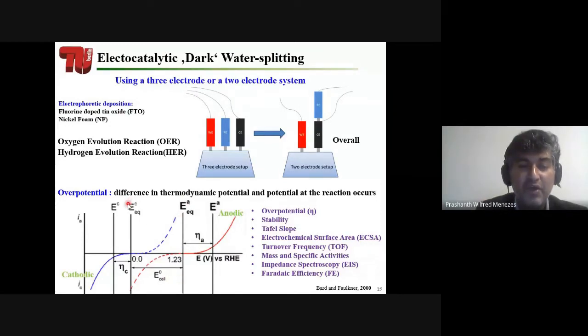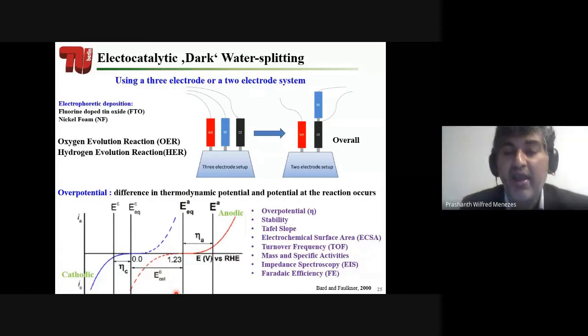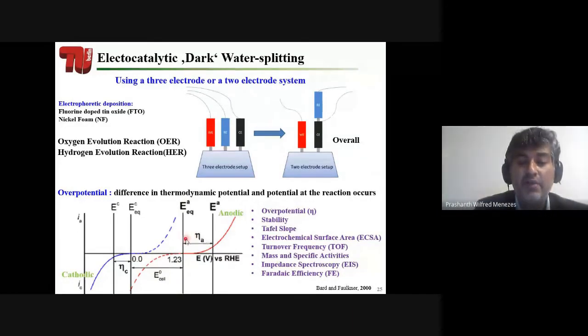Similarly, this is for hydrogen evolution reaction. What you can see is that this is the thermodynamic potential for hydrogen evolution reaction, and then whatever potential we put extra is our overpotential. As I said, no catalyst can show this potential because this is the very ideal condition and this is not possible. However, you can always judge whether your activity is good or not by these overpotentials.